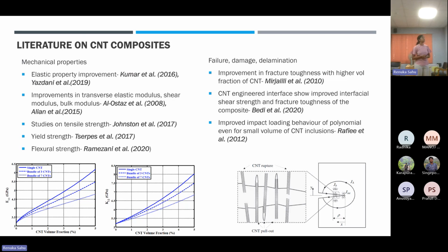Further, CNT composites show definite improvement in mechanical properties. As you can see, as we are increasing the CNT volume fraction, we are getting good increment in the elastic modulus and the bulk modulus. Even transverse elastic modulus and yield strength, flexural strength, all of these improve.